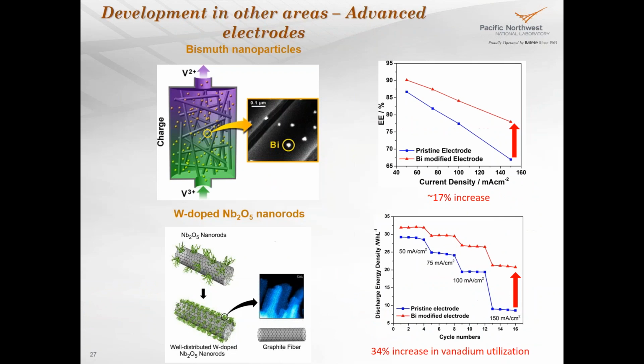So I also talk a little bit about other developments, such as the advanced electrode. What we do is we put the catalyst, such as bismuth or niobium oxide, to increase the energy efficiency of the system. You can see from the right side figure it also increases the vanadium utilization ratio. We know vanadium is expensive. There's nothing we can do with the price of vanadium, but what we can do is to use it more efficiently. That is showing here to increase the utilization of the vanadium.